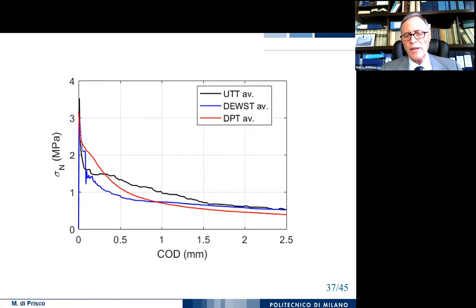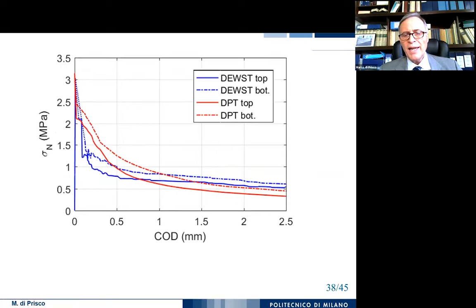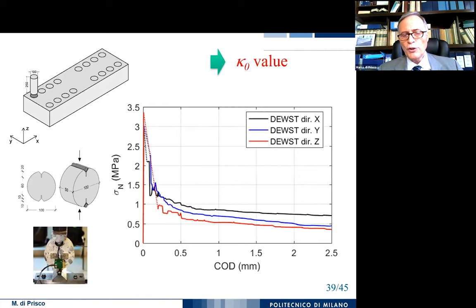They are not so different, especially in the second part we are interested in, related to the pull-out mechanism. And you see also that with the double edge and double punch, we can distinguish the top from the bottom. And usually in the bottom, you have something more than in the top, of course. And we can also use a double edge wedge splitting test to evaluate the kappa0, and you can see the difference if we change the direction of the uniaxial force. And so this expresses the difference between the different directions, and this difference can be computed by means of the double edge wedge splitting test.